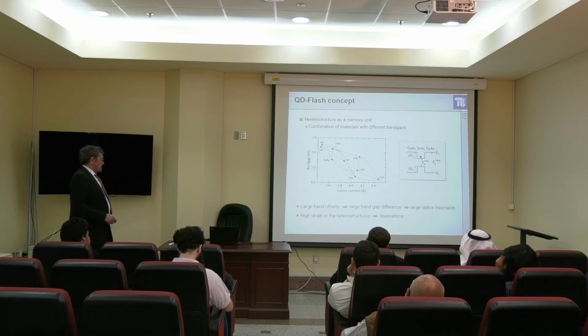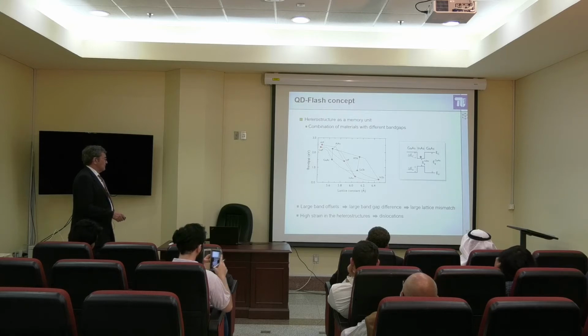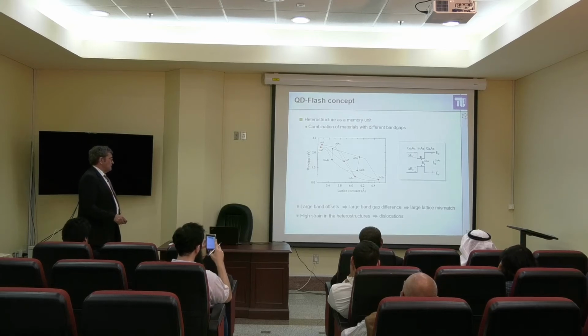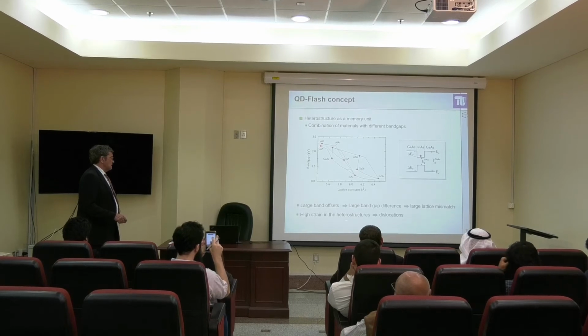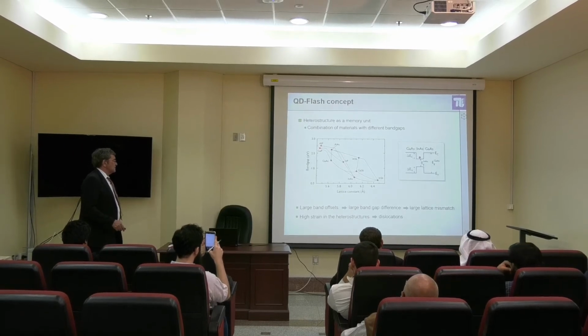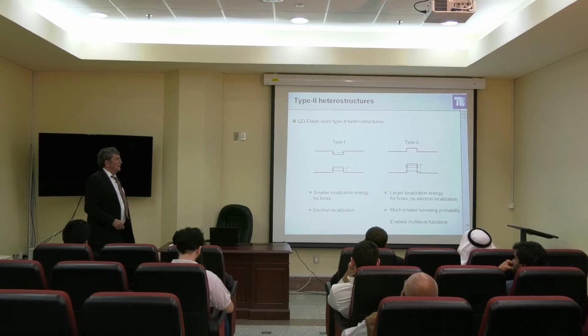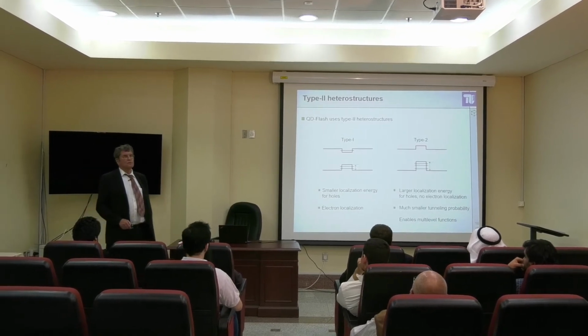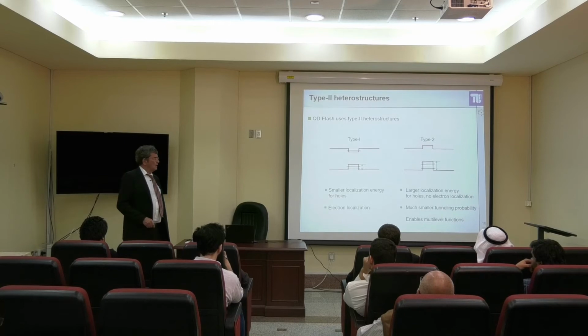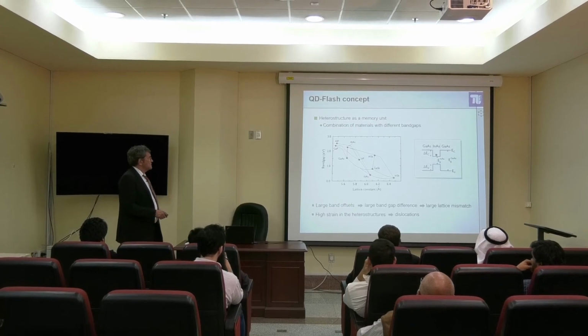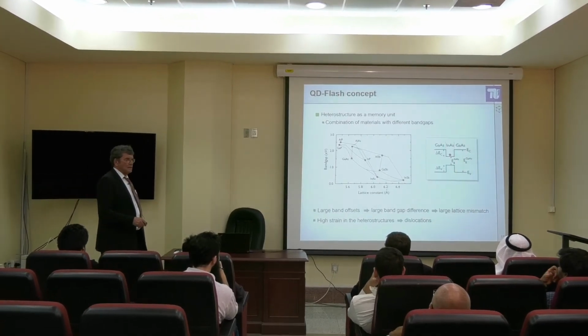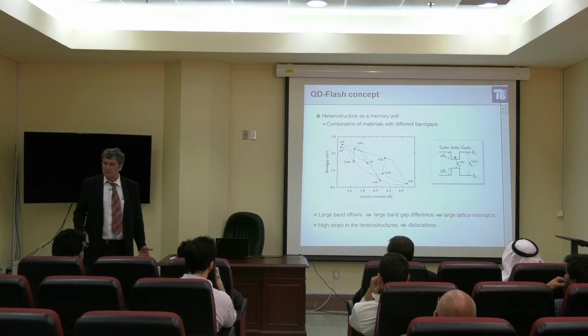Large band offsets Band gap difference, large band gap difference, large lattice mismatch, but high strain in the heterostructure, dislocations. Now, what I introduced for the first time is: don't use these types where, when you inject carriers, you can keep electrons and holes.